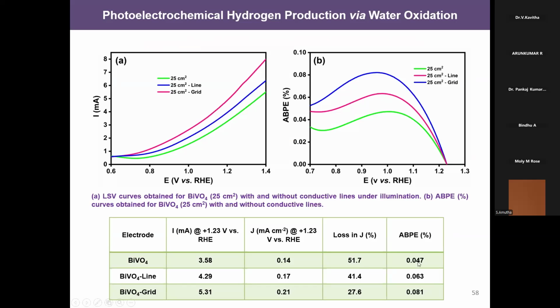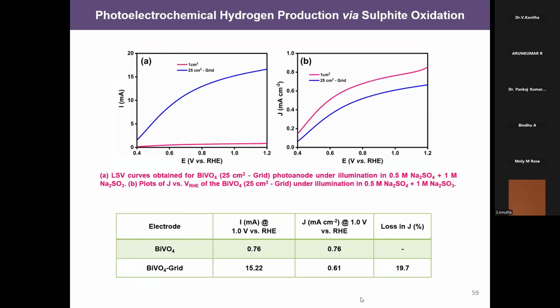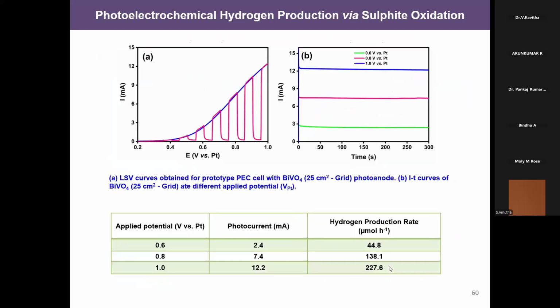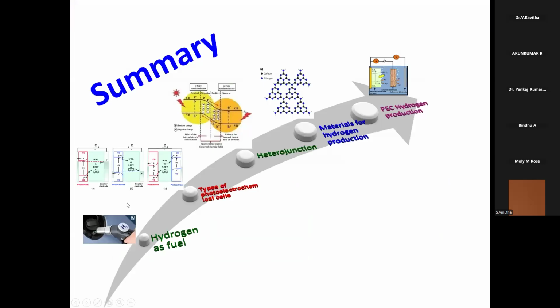So here it seems we have reduced the efficiency loss from 51 percentage to 27.6 percentage. Further, we added the sacrificial agent. Then we reduced it to below 20 percentage. Then we checked the hydrogen production rate. So we are able to get 227.6 micromoles per hour. The stability also shows excellent results. So this is what we have developed. So this is the overall summary of the presentation.